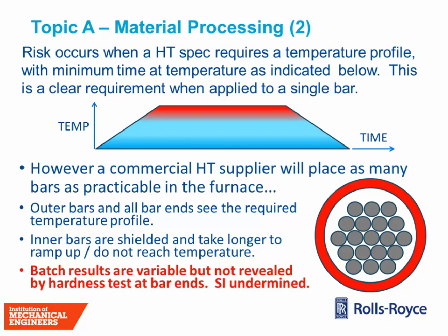So here's an example of something that can go wrong. If you've got a temperature profile, and I've just shown it very simply as temperature against time, that you write down in words in a specification, ramp up at this rate, hold for this period of time, ramp down at this rate, then you've got a requirement that's very simple and very clear, and if you apply it to a single bar, probably relatively easy to achieve. But if you go to a commercial supplier and ask them to heat treat large quantities of bar stock, they will understandably place as many bars as practicable in the furnace.